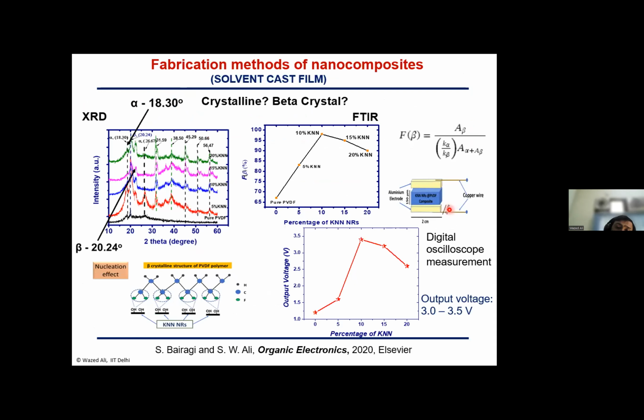And then we have incorporated this filler into PVDF, and first of all, we have proved this concept in the form of composite film, and this film is characterized for different kinds of structural features. For example, if you characterize pure PVDF film, then we are getting some beta concentration, for example, 65% beta crystal phase, which is desirable. But the moment we add this filler structure, for example, 5% KNN, 10% and so on, the beta percentage of the PVDF also increases, because metal oxide has different kinds of hydroxyl groups on the structure surface. So it will have some kind of interaction with the fluorine group of the PVDF, and that essentially helps the formation of more beta phase in the PVDF structure, right? So that kind of concept has been proven over here, the arrangement of the filler within the structure to have more beta phase from the polymer part as well.